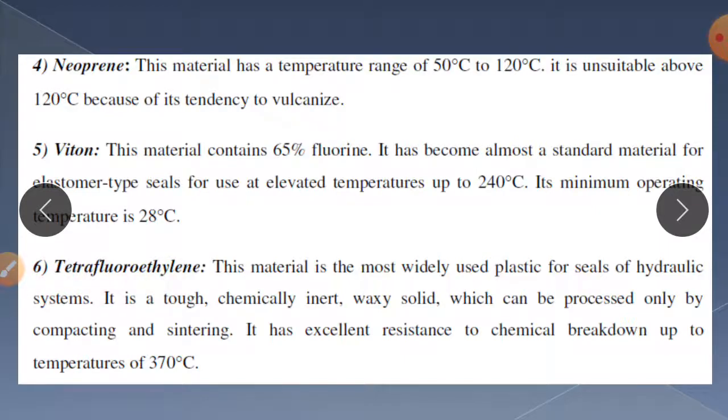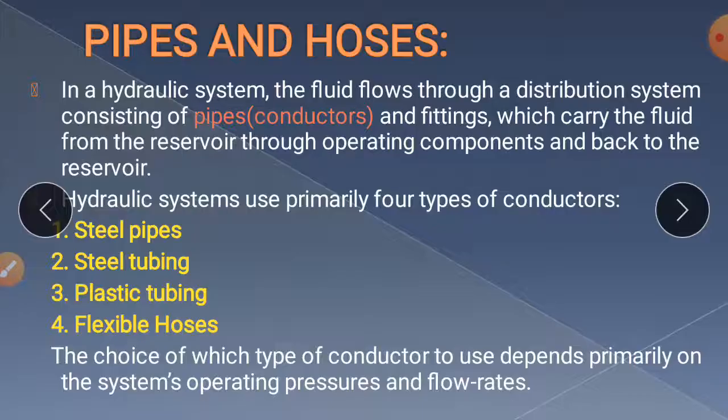Next, tetrafluoroethylene. This material is the most widely used plastic for seals of hydraulic systems. It is a tough, chemically inert, waxy solid, which can be processed only by compacting and sintering. It has excellent resistance to chemical breakdown up to a temperature of 370 degrees centigrade. Okay, this is all about the seals.